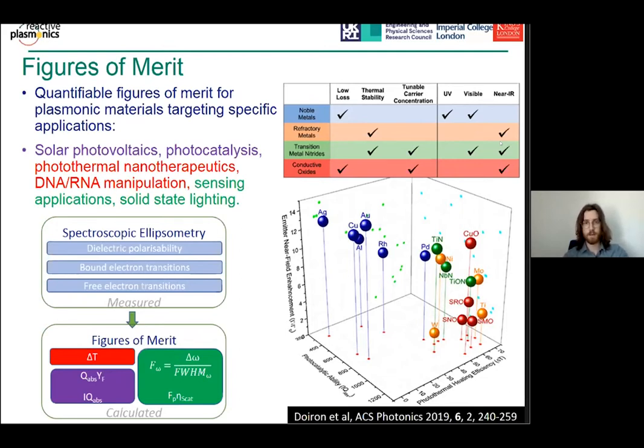So we deposited thin films of this wide range of materials. We measured their optical properties using spectroscopic ellipsometry and fitted this with a Drude-Lorentz model. And then this data we input and combined with Mie theory in order to identify these quantifiable figures of merit. So I'll just take you through a couple of relevant examples here.